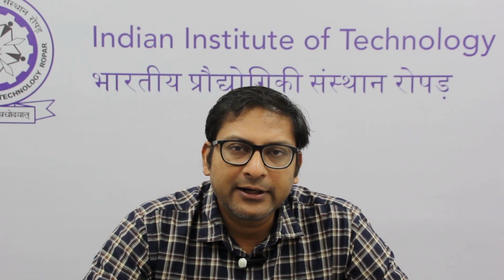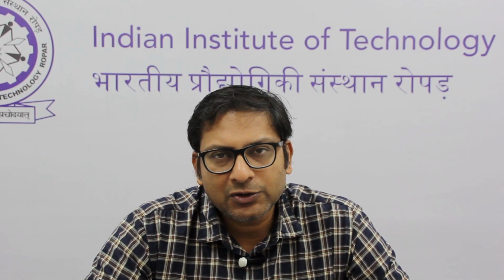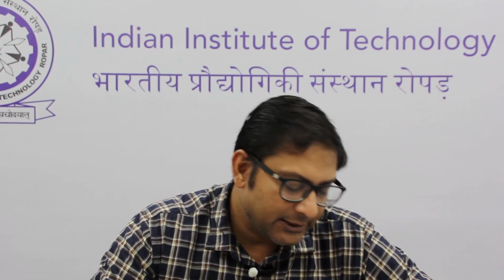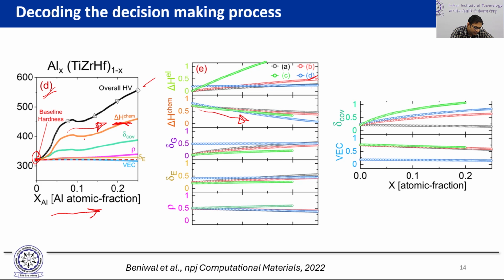So the chemical enthalpy decreasing means now the bonds that are being formed are getting stronger and stronger. This is something that people have also seen with the addition of aluminum to different high entropy alloys. It tends to promote a more ordered structure, which indicates stronger bonding taking place. And so as the bonds are stronger, breaking those bonds to create the plastic deformation required is also going to become more and more difficult, and this delta H chemical is therefore adding quite significantly to the hardness of the alloy.